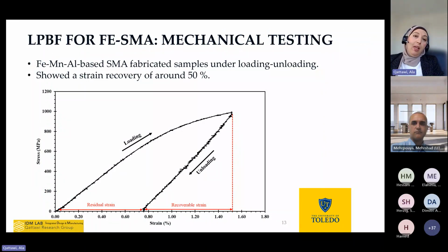The next step in the analysis was, okay, we produced a good part. It has shiny surfaces. The surface roughness is acceptable. Hardness is acceptable. Density is acceptable. Now it's time to look at the mechanical properties of those components. The initial study showed that we actually achieved good values for the strain recovery within this alloying system.